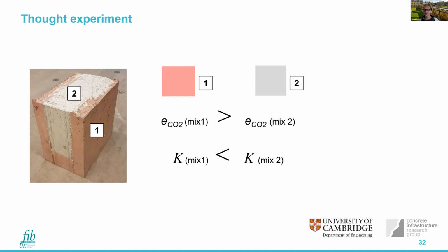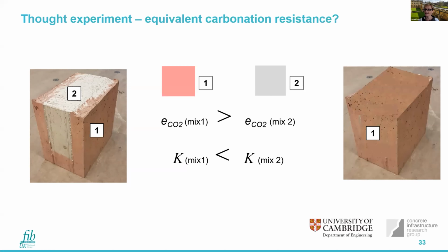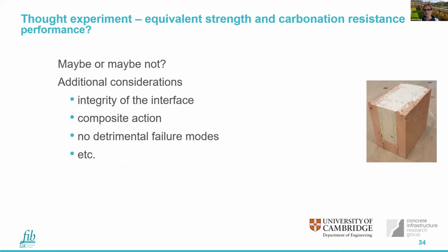Are we then comfortable with the idea that the carbonation resistance of the tailored element is equivalent, say, to the carbonation resistance solely of mix 1? And you might say, okay, if the carbonation front hasn't progressed into the gray material, I'm happy with that. But if it does progress into the gray material, I'm not happy with that. So what do we now mean for equivalency of performance when we start to think of new innovations, both in terms of the materials, the structural forms, and how we put together our structural elements? And so it comes back to, are we happy with this? Maybe or maybe not. And we might have additional considerations we'd investigate, the integrity of the interface, the composite action, no detrimental failure modes, et cetera, et cetera.